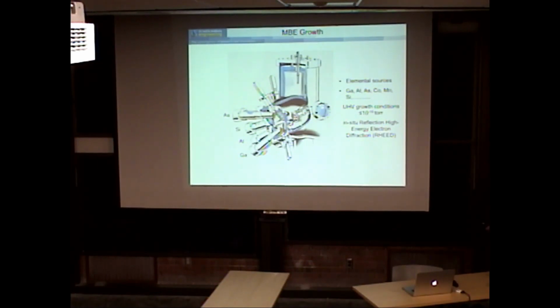So we put the elemental sources we want in crucibles, with heaters around them to evaporate. The shutter in front opens and closes to let the flux hit your sample, which sits on a heated stage here. And then we have liquid nitrogen. You can see this blue stuff is internal liquid nitrogen cryopaneling to keep a good vacuum. Typically our growth background pressure is below 10 to the minus 10 torr. Another nice thing is you can use electron diffraction to actually look at what you're doing while you grow.